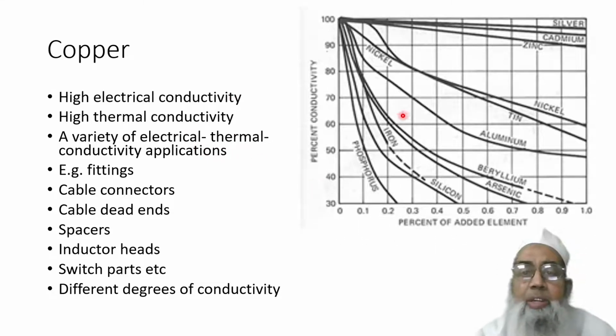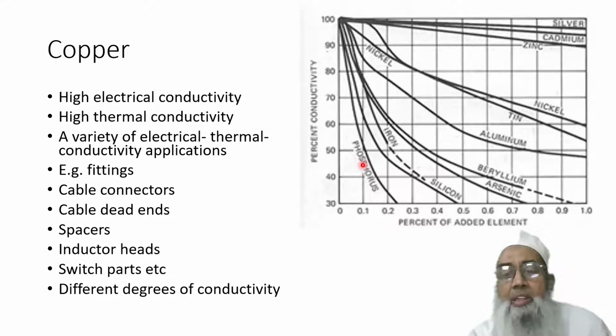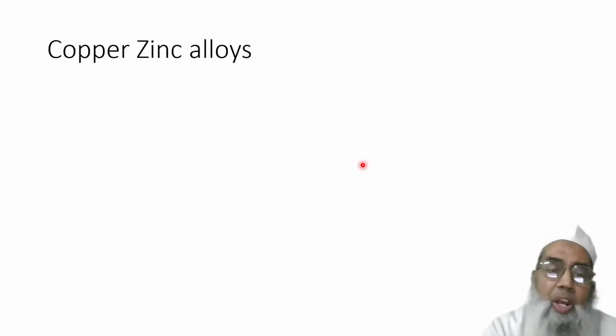This figure shows that silver and the others reduce the percentage of conductivity in the alloy, and the worst is phosphorus. A small amount of phosphorus, as the figure shows, causes a very significant deterioration in the conductivity of the material. Therefore this has to be properly controlled, and a smaller amount of phosphorus should be there in the alloy.